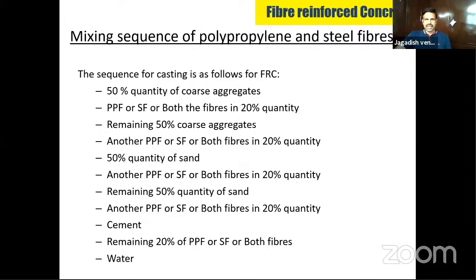First, place half the coarse aggregates, put in 20% of the fibers and mix. Again, the remaining half of the coarse aggregates and another 20% of fibers, and mix. Then 50% of the sand, 20% fibers, mix. Again 50% sand and 20% fibers, mix. Then lastly put in the cement and rotate, add the remaining 20% of fibers, add water at last, then mix it and place it. You have to follow this mixing sequence because the fibers have to be distributed randomly. If you don't, the lumps of fibers will settle somewhere.